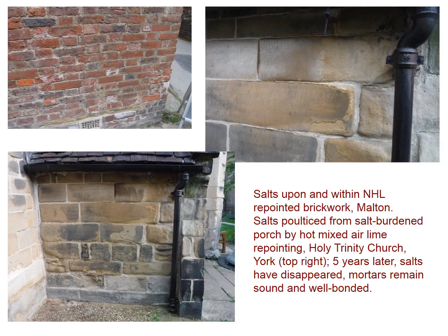Salts here upon brickwork pointed with NHL, but of course built with a hot mix in mortar. Salts on the top right, poulticed from a salt burdened porch of Holy Trinity Church, which had already caused significant decay of the arrises of the stonework. And shortly after repointing, these mortars are not white. They're showing those salts. Those salts are being poulticed from that fabric. 5 years later, those salts have disappeared, and the mortars remain sound and well bonded.